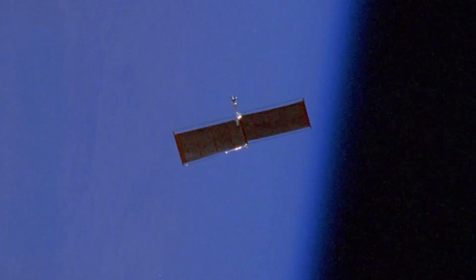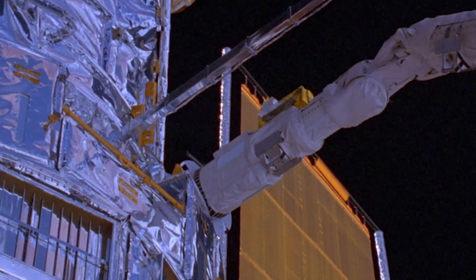So we concluded that the best design for Hubble was to use this aluminized Teflon, but without the protective coating. When the new arrays were launched, the telescope worked and there was no thermal jitter.